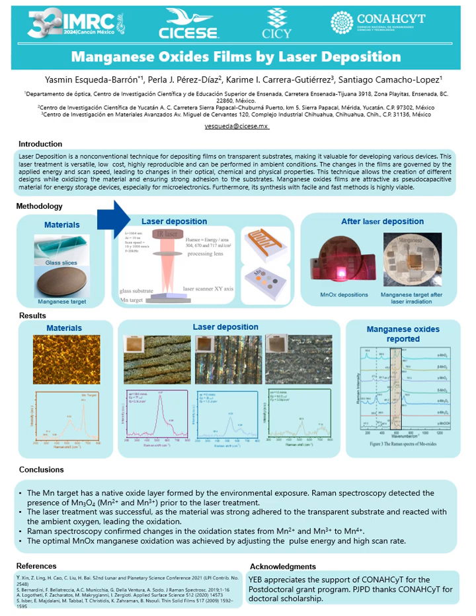The laser used has a wavelength of 1064 nanometers, a pulse duration of 10 nanoseconds, and is equipped with a galvanometric mirror system that deflects the beam to scan in stroke patterns, covering a larger area. This type of laser deposition is particularly useful for directly designing devices on the transparent substrate, for example sensors or antennas, as illustrated in the images.